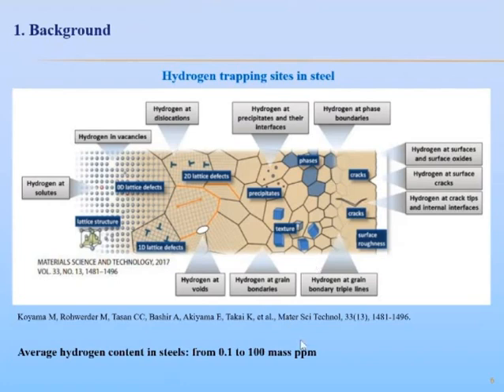For instance, the average concentration of hydrogen in steels is within the range from 0.1 to 100 ppm. Moreover, hydrogen is diffusible even at room temperature, and this effect is further enhanced in the presence of stress localization.